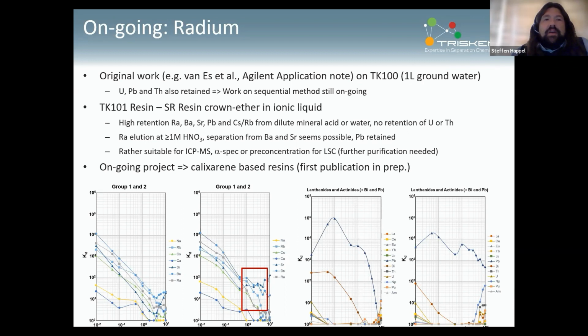But the idea is to try to elute radium on its own by keeping barium and strontium and lead on the resin and having a pure radium fraction. Not entirely sure if that's going to be pure enough for LSC measurement. It's probably going to be good enough for ICP, for maybe mass spec. For LSC, I feel we still need to improve the method quite a bit. But at the end of the day, it's not really what we're looking for. There are still quite a lot of elements that are separated at the same time.